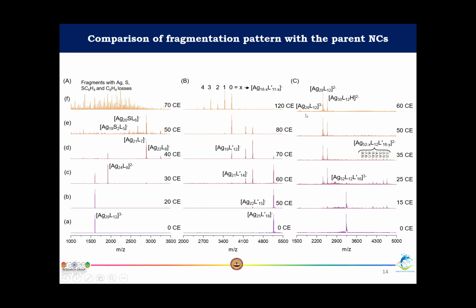You know, Swetashree, there is some bit of an issue with what you just now said. You are colliding with a mass which was some x in the case of the parent clusters. When you made a dimer, the mass is at least 2x, or more than that. So although the kinetic energy is the same between the colliding partners, effectively the per atom energy transferred to this dimer is less.